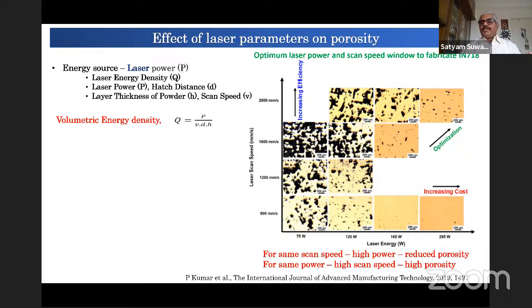Porosity is a very important negative attribute of this process, because these are mainly powder-based processes, and all powder-based processes are associated with some amount of residual porosity. So research is always carried out first to optimize the porosity levels, and in this slide I am showing the laser energy versus laser scan speed.